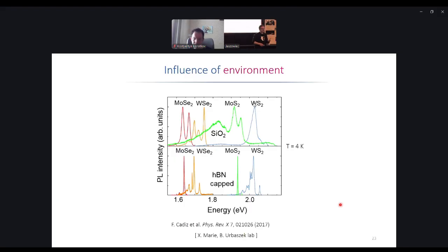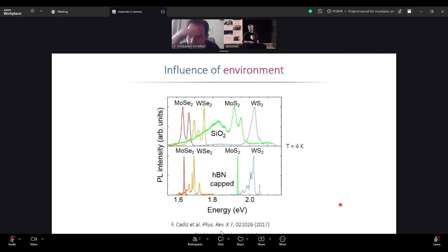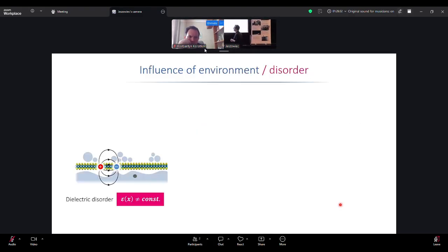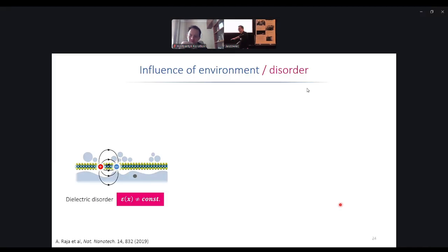But this is an observation that leads, at least in this field, to a relatively standard procedure of what we do with the crystals, how we get narrow optical lines: place two hBN plates around the monolayer. And one of the reasons why it works is the following. This is a schematic, but usually, even if I present you this PowerPoint physics, your environment is not homogeneous. If you place a material on any type of substrate, the substrate will have some morphology, some changes of its height. The material will not exactly follow it.